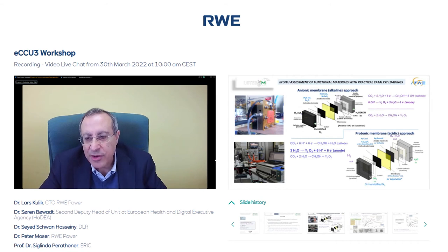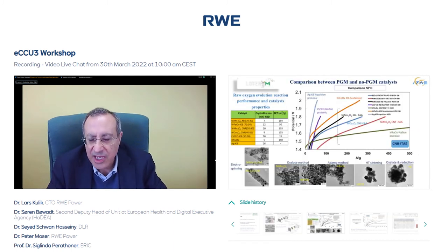In the protonic environment, we have a perfluorosulfonic membrane separator. And since the environment is acidic, we need to use essentially precious metal electrocatalysts at the anode due to the high operating potential and the needed electrochemical stability. So essentially iridium, ruthenium oxide. In this case, we have water that is oxidized to oxygen at the anode. And in this case, we recirculate just pure water at the anode. So two different strategies, two different operating approaches for the alkaline and the acidic environments.